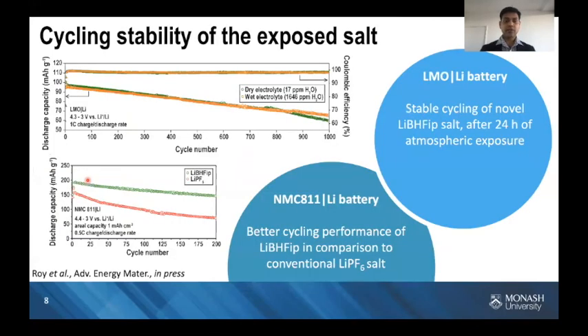To understand that, what I did was construct an LMO lithium metal battery with the exposed electrolyte after 24 hours. And as we can see in this figure, the novel fluoroborate electrolyte, even after its exposure, does accumulate a high amount of moisture, around 1600 ppm. However, the cycling behavior of the wet electrolyte is not very different from the dry one, suggesting that the salt is not only stable against moisture, but it also helps to limit the negative effect of moisture presence in a lithium metal battery.